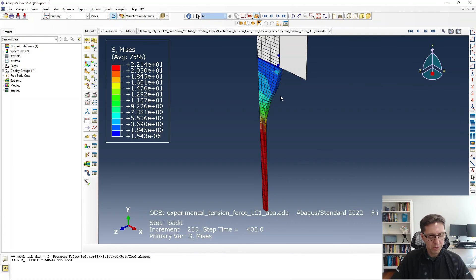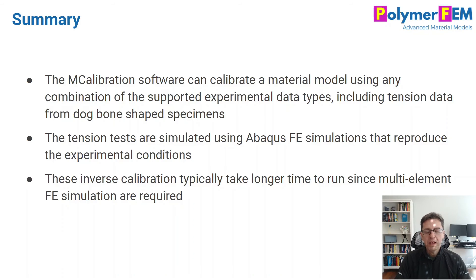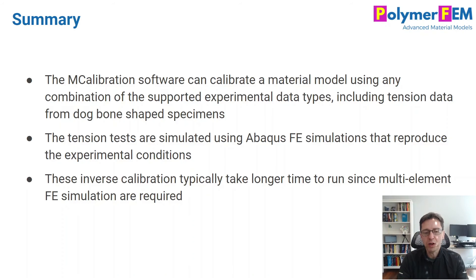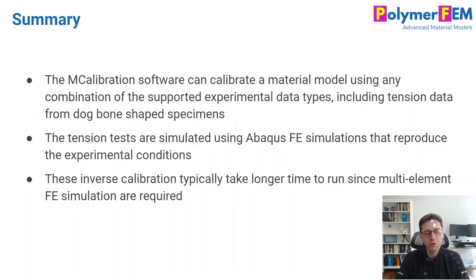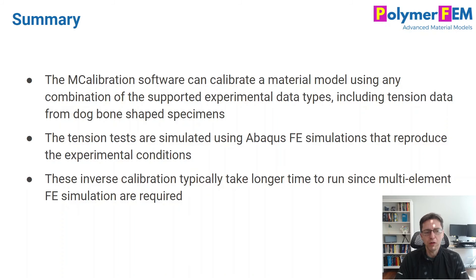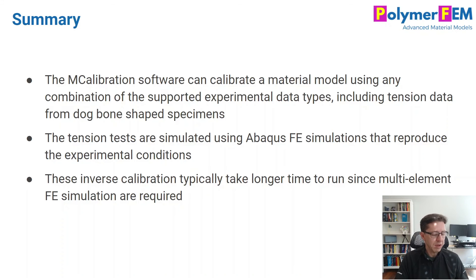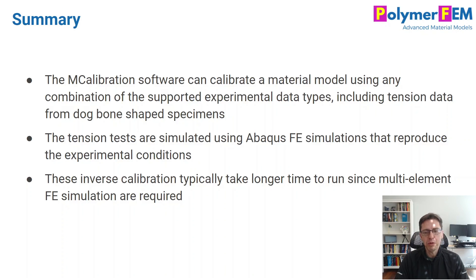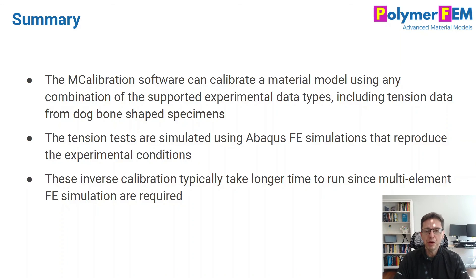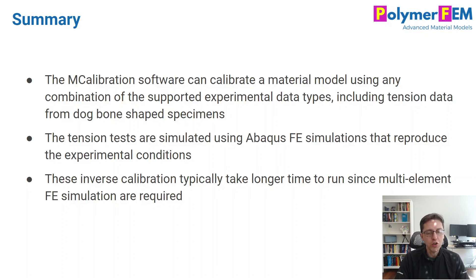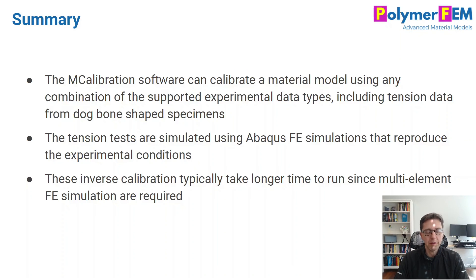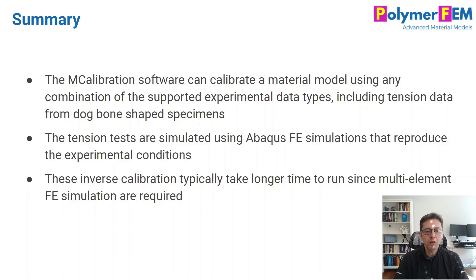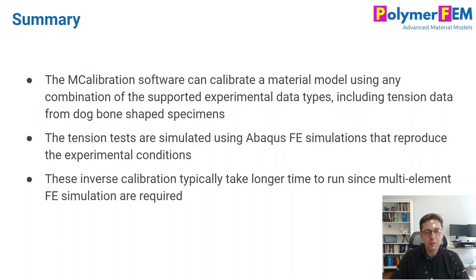So let's summarize. If you're interested in analyzing force displacement data from a tension test, you're using one of these standardized specimen geometries, which is what I would recommend, and if you're focusing on Abaqus as your FE solver, then you should consider using this approach. You can use this to calibrate a material model to the force displacement results. You can try to use DMA results too, but if a material is undergoing necking, that is not so good. If you don't have necking, that would be perfectly fine and would run faster. But if you have some necking, the approach I talked about here would be the preferred method to analyze the data. It works well - you get an accurate material model. It does take longer because you have to iterate a finite element simulation with Abaqus, but it's a refinement. You can do the majority of the calibration using approximate stress strain data.